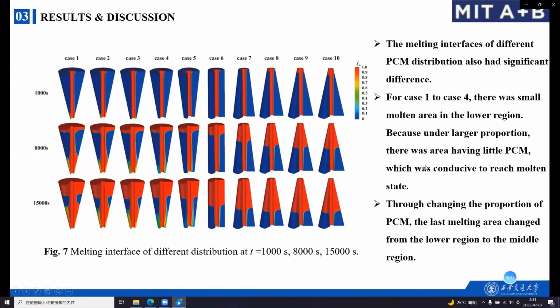And the next was the melting interface. From this picture, we could conclude that the melting interfaces of different PCM distribution also had a significant difference. At 1000 seconds, for case 1 to case 4, there was a small molten area in the area near the copper tube. Because under larger proportion, there was an area having little PCM, which needed a little heat to reach molten state.